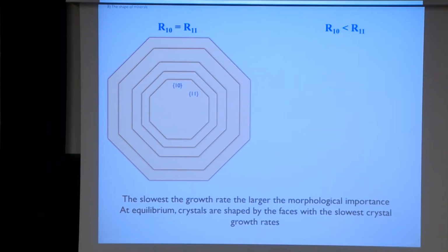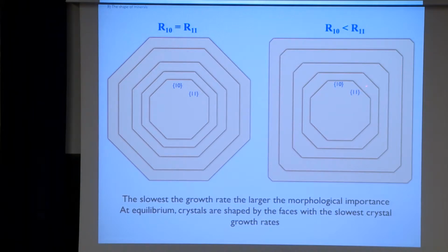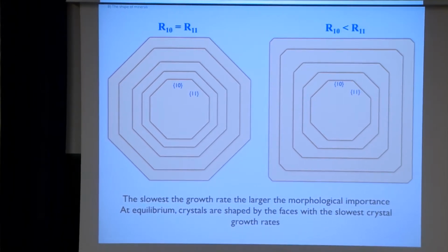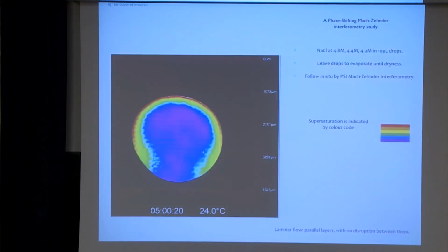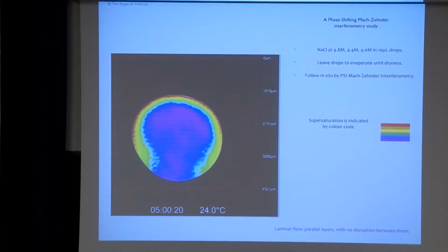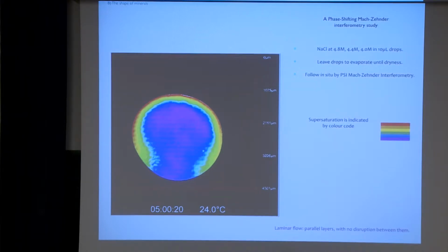Okay, but now we start with the same crystal, but the growth rate of the 1 1 faces is faster than the growth rate of the 1 0 faces. Finally, the 1 0 faces are the only ones that stay. Okay, so it is important to realize that the shape of the crystal is a matter of the internal anisotropy of the crystal structure. So you can have variation of this, different kinds of physical environments that change this law, which depends on the crystal structure. So if we consider not only the crystal structure but also the growth environment, then things can change.